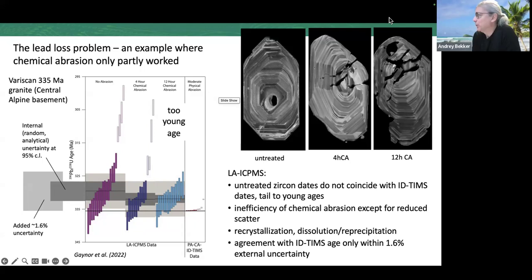But what if you anneal twice, before and after chemical abrasion? Would it help in terms of making zircons more stable? I don't think so, because it's not the question that the zircon gets weak, gets soft or something. The question is that only a skeleton is left, it's very fragile. And sometimes, especially zircons like Don described, which have internal high uranium zones, they completely fall apart. When you look in your microcapsule, you have 1,000 very, very small fragments you cannot handle anymore. And this is what remains.